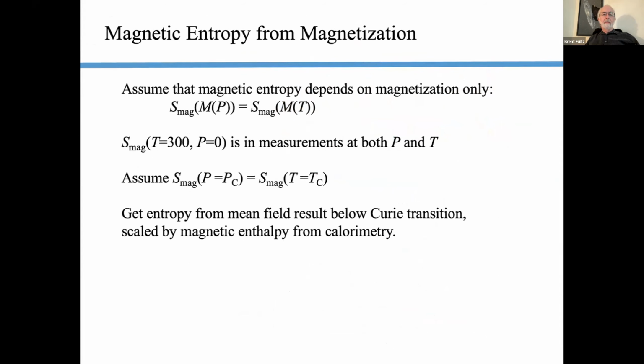So we have to get the magnetic entropy, and we have some endpoints that we know. We know that there's no magnetization at the Curie transition, either in pressure or in temperature. We'll assume that the magnetizations are the same there. They're just short range order. Now, the short range order might vary a little bit between these two. We also know we have an endpoint at room temperature, which is in both sets of data. So we can get the entropy from a calculated curve below the Curie temperature, and we scale it by calorimetry. We have magnetic enthalpy from calorimetry, and fortunately, classical thermodynamics comes to the rescue here.